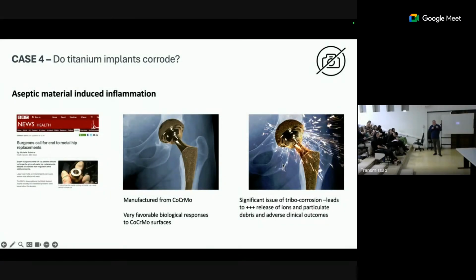And what they found out was that if you didn't put a bearing in here and you went straight on metal on metal, here we're using cobalt chrome molybdenum, you generated conditions where not only did you have wear particles, but you're also producing a lot of solution species.